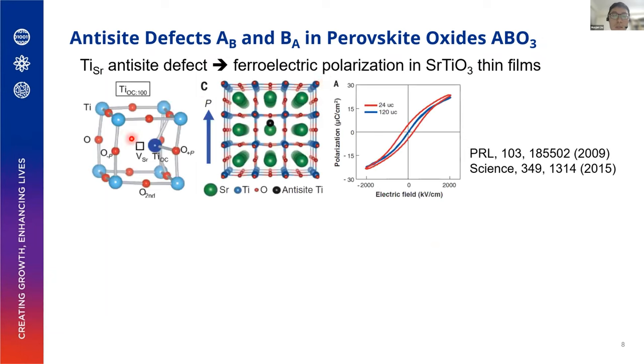One example is in strontium titanate thin films, where you can have a film with strontium vacancies so that the extra titanium can occupy the strontium position. But because of the smaller ionic size of titanium, it cannot effectively bond with all the oxygen, so it has to shift into an off-center displaced position. This gives rise to local ferroelectric polarizations, and this is responsible for the ferroelectric polarization observed in this film, which is otherwise a paraelectric film.